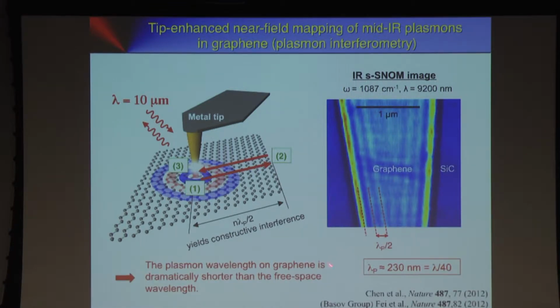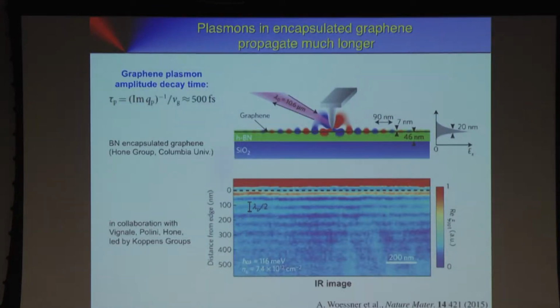So if we measure that, we come up with a plasmon wavelength of 230 nanometers. The photon wavelength is 10 micrometers. And that corresponds to a wavelength compression of lambda over 40. So that's quite impressive. And this actually triggered a lot of interest in the field, and there's a lot of potential. Now these waves don't propagate very long because this was done with graphene that was not of the highest quality. But if one uses graphene that is embedded in boron nitride, this is high mobility graphene with mobilities that are enormous, then we see here that these fringes persist much more, and we see many oscillations.